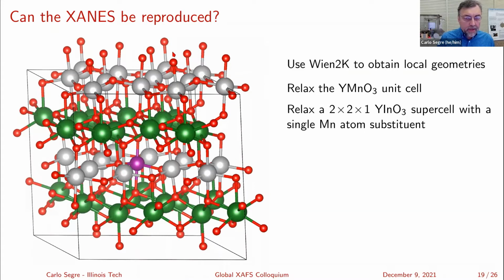It doesn't show anything down here because they moved into the lower cell after the relaxation, and then I put a manganese ion in the middle. My hope was that this manganese ion would be far enough away from the next manganese ion over that it would be sufficient to give me something reasonable. And I didn't want to make the unit cell so big that it would take forever to do the calculations. Because these typically use periodic boundary conditions, there would be another manganese out here, another manganese up here, and so on. So I put a single manganese substituent in and I relaxed the system, and this is what I got.